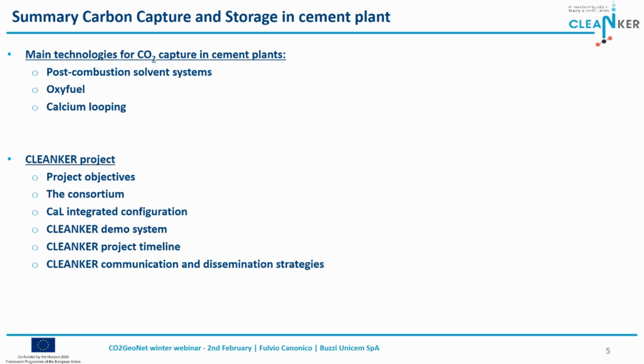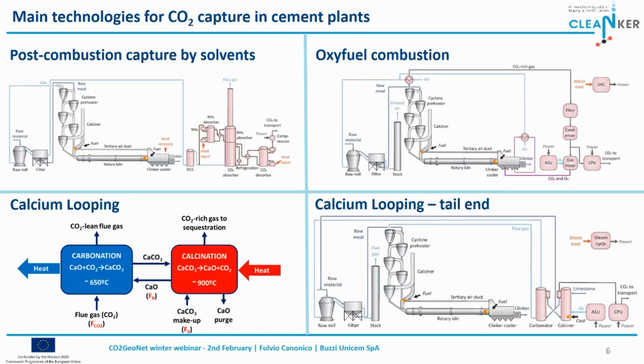So there are several technologies which are already used at pilot scale or even at semi-industrial scale in cement plants. So post-combustion, oxy-fuel, but even also innovative solutions like calcium looping. So please go to the next slide. So you probably know the post-combustion solvent systems are systems based on a solvent that is able to dissolve CO2 and to remove the CO2. This is a solution which is already on the market, so we could already buy one of these technical solutions and install it in our plant. The advantage of post-combustion capture by solvents is that we don't have to change our process, so we can keep the cement plant as it is and basically add this post-combustion solution at the end of the process and operate it.